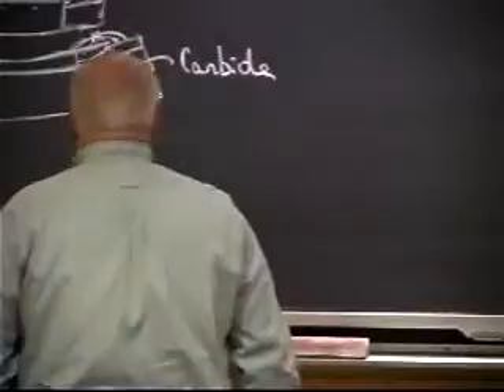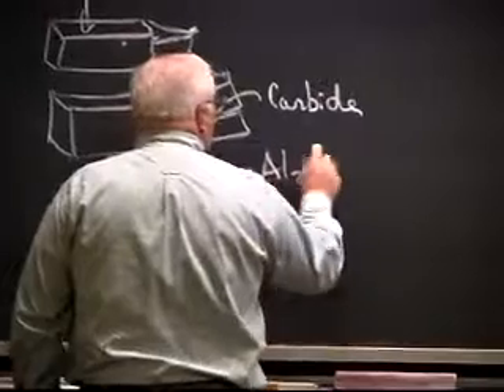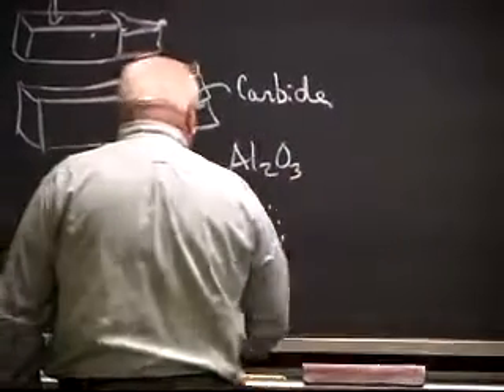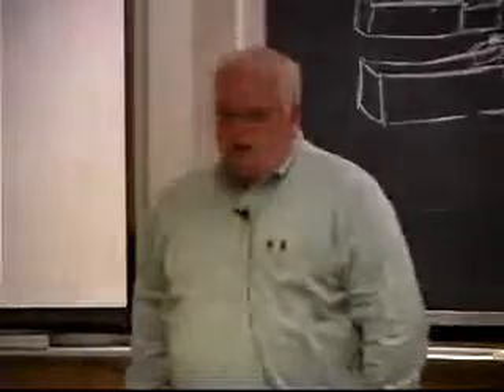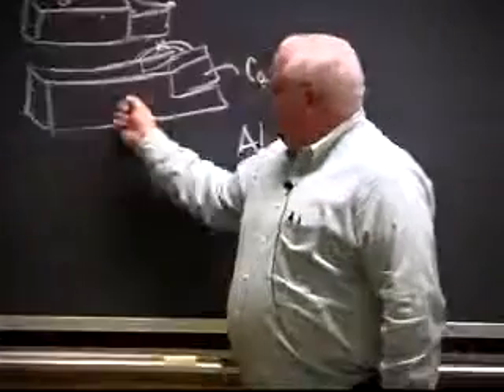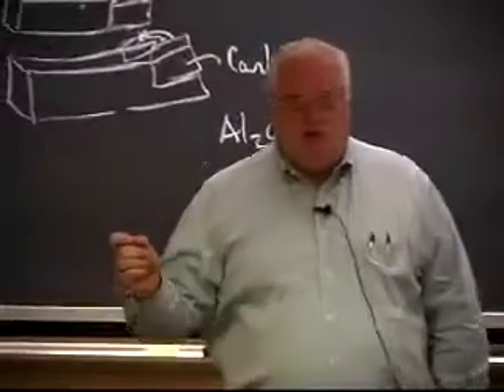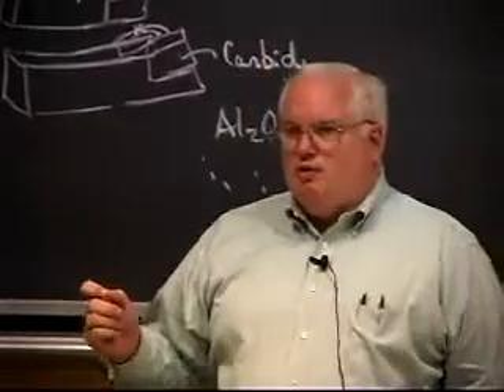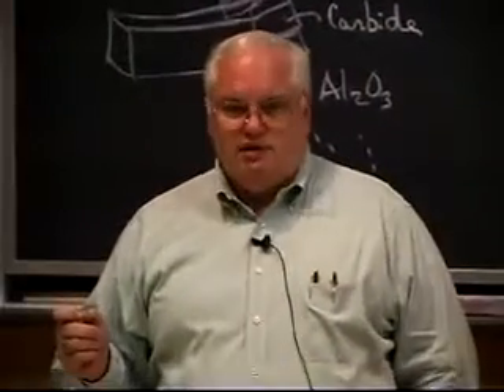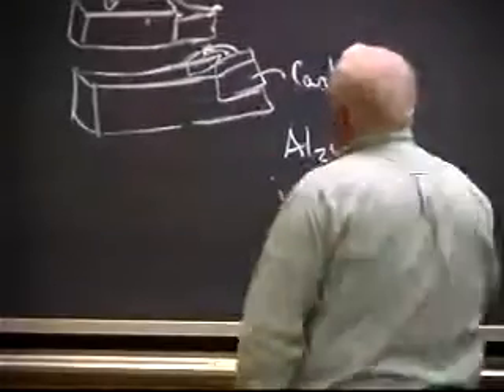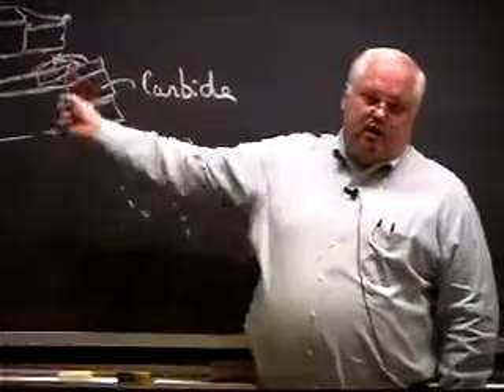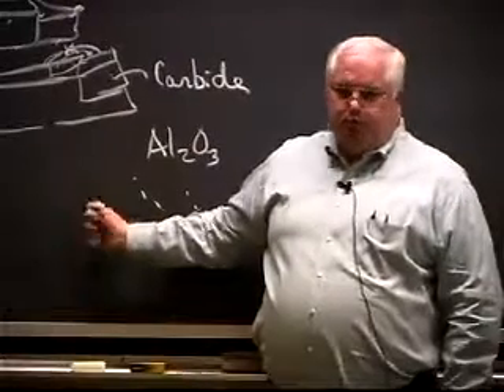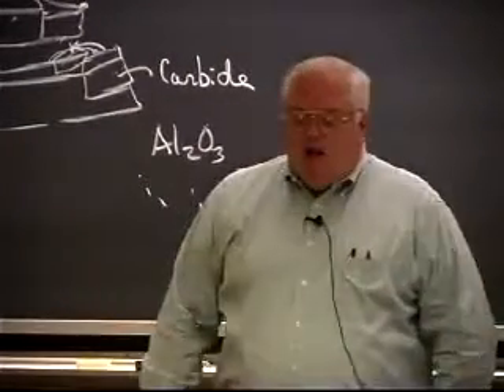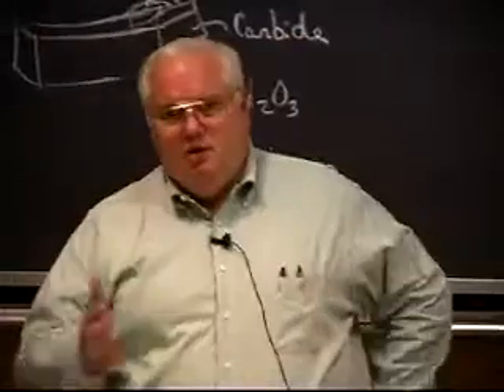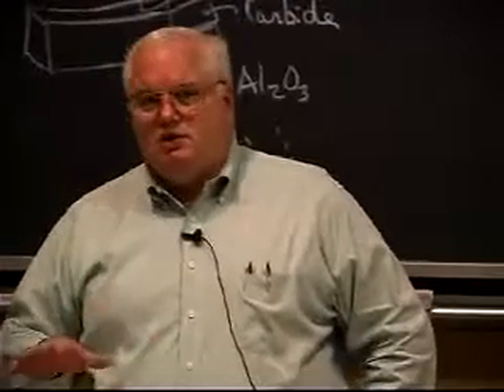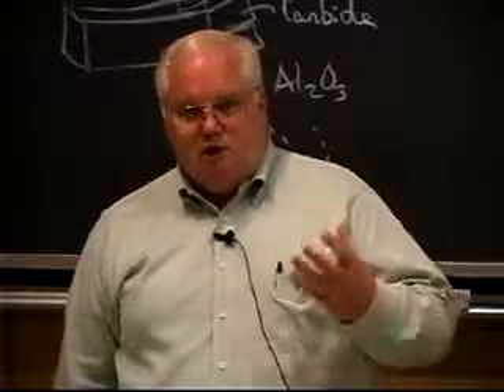And so instead of a carbide, they started out with aluminum oxide, and then they get to all kinds of fancy ceramics now. And what's happened is the cutting speed in the last 30 years on machine tools has increased by probably a factor of 30 to 40 times because of this. If I could go at 100 surface feet per minute here, I might be able to go to 3,000 surface feet per minute now with the fancy ceramics. And that has had a tremendous effect with numerical controlled machine tools in terms of reducing the cost of lots of things that are complex parts that we have to machine.